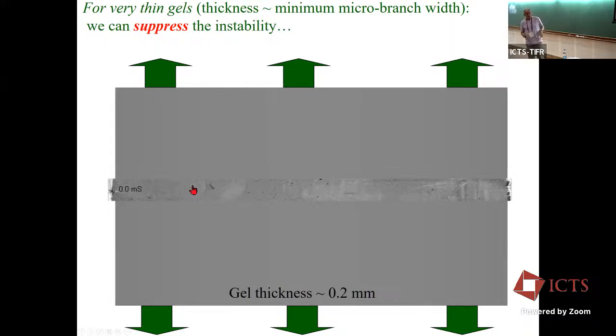Now, when we did that, we got a surprise. We expected that when we get rid of all the instabilities by suppressing them, we would see cracks smoothly accelerating up to the Rayleigh wave speed and just stay there, and everybody would be happy. What we found is we got cracks that smoothly accelerated up to the Rayleigh wave speed, and then slightly beyond the Rayleigh wave speed, something funny happened. And I'll show you what that is.